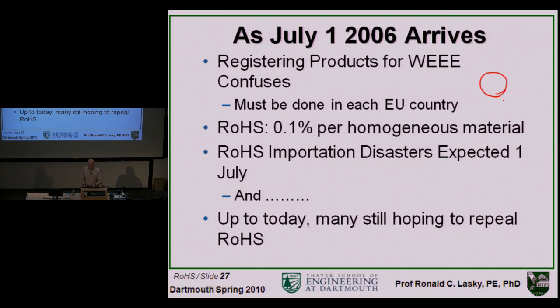If you take the mass of the screw, the hexavalent chromium is just a very thin coating on the top. If you take the mass of the screw and the mass of the coating, it's probably much less than 0.1%. But this is not what the European Union meant. If you take any piece of material, literally the first atomic layer of the surface of the screw has to be less than 0.1% hexavalent chrome. So obviously you can't use hexavalent chrome.